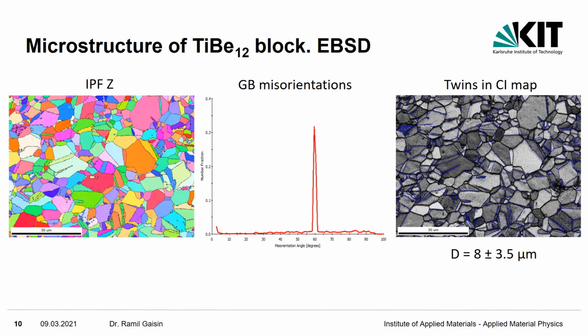Electron backscatter diffraction showed that the material is homogeneous without any microtexture. There are a number of grain boundaries with a 60-degree misorientation associated with twinning. In the right image, the twins are highlighted in blue, and disregarding these twins, the grain size was determined as about 8 microns. This is quite small, taking into account the high pressing temperature of 1250 degrees.